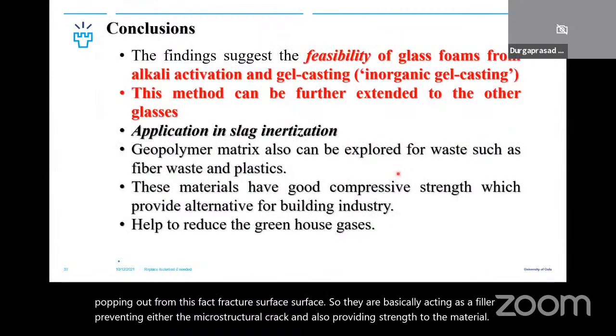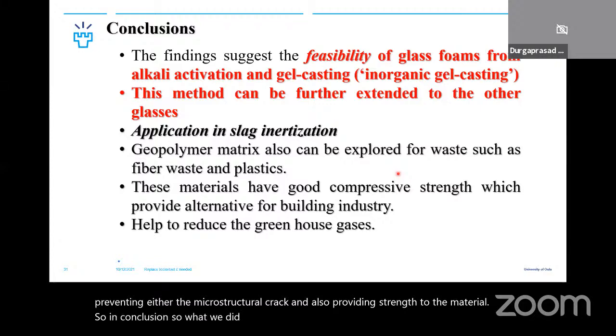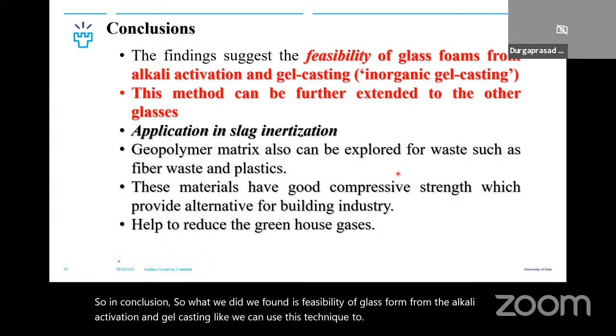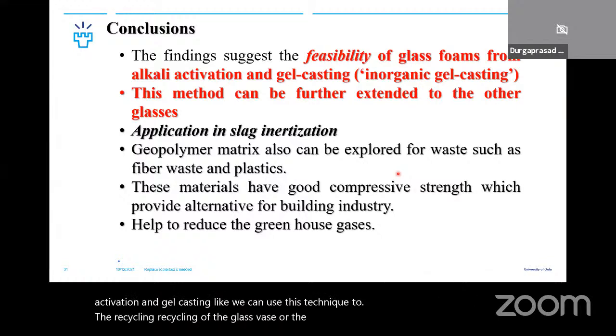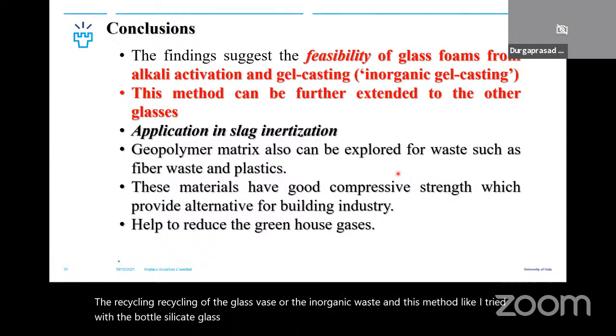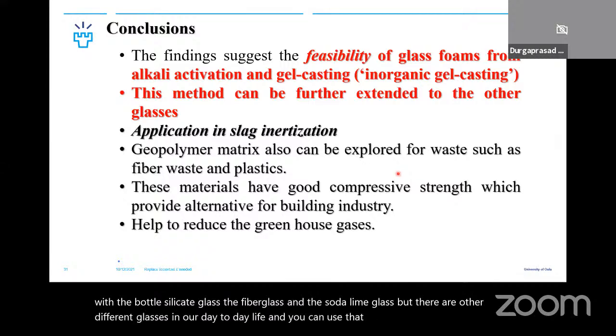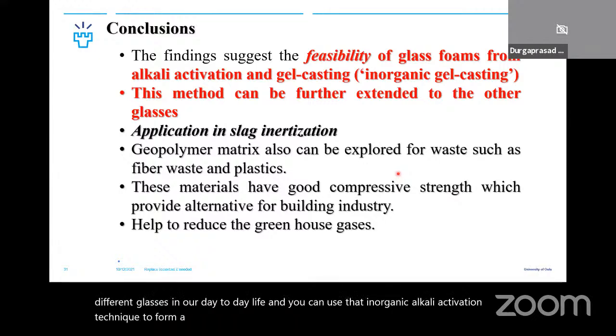So in conclusion, what we found is the feasibility of glass foam from alkali activation and gel casting. We can use this technique for the recycling of the glass waste or the inorganic waste. And this method, I tried with the borosilicate glass, the fiber glass, and the soda lime glass, but there are other different glasses in our day-to-day life, and you can use the inorganic alkali activation technique to form a foam glass, which can be good for the green environment, towards saving the environment.